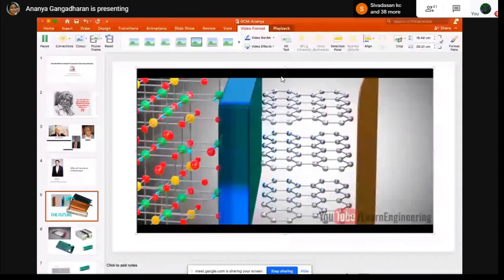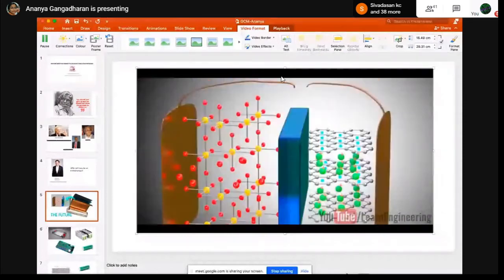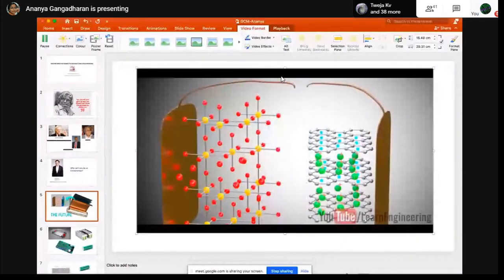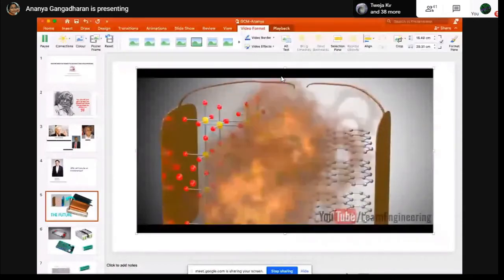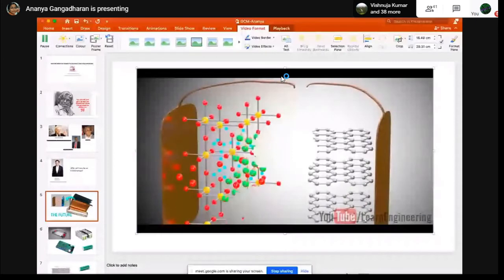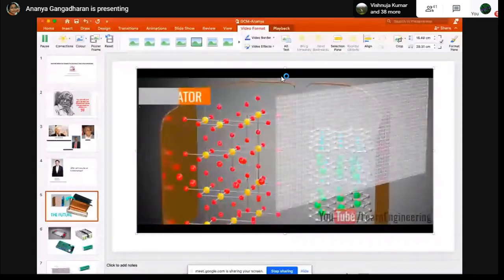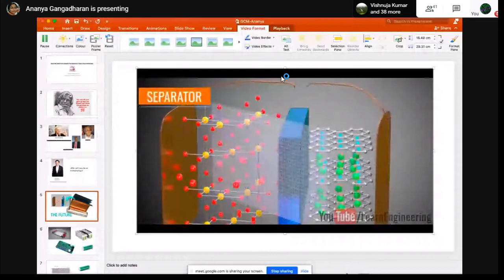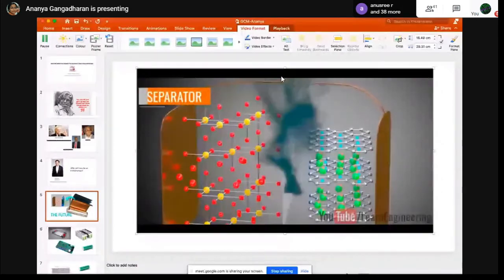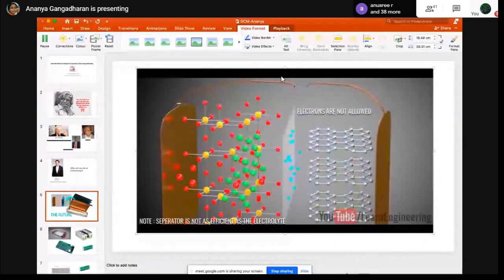If the internal temperature of the cell rises due to some abnormal condition, the liquid electrolyte will dry up and there will be a short circuit between the anode and cathode, and this can lead to a fire or an explosion. To avoid such a situation, an insulating layer called a separator is placed between the electrodes. The separator is permeable for the lithium ions because of its microporosity.